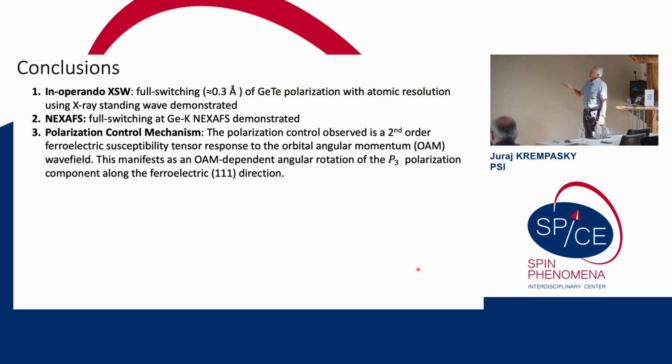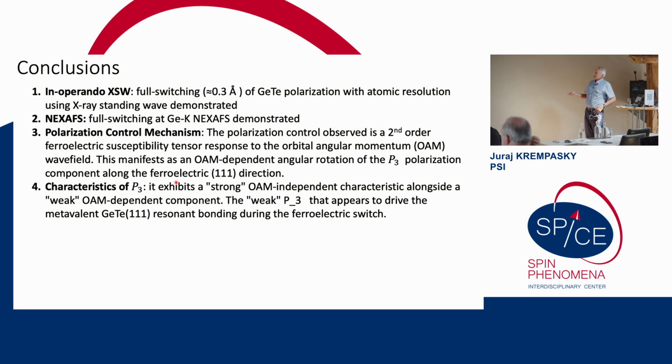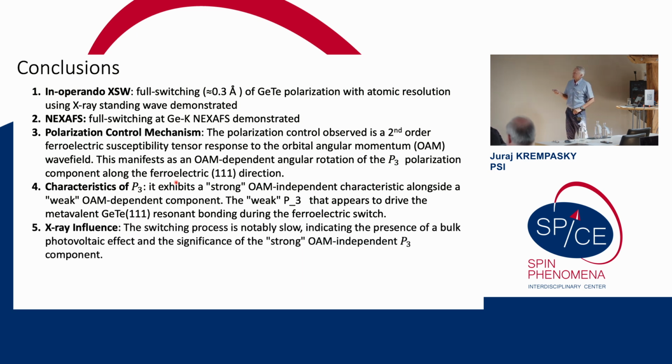lies in the second order ferroelectric susceptibility tensor response to orbital angular momentum. And this manifests as an angular rotation of the P3 polarization along this ferroelectric direction, which is ferroelectric active. And as Václav will explain in a minute, there are these strong and weak components we need to consider. And importantly, the switching process I showed is notably slow.